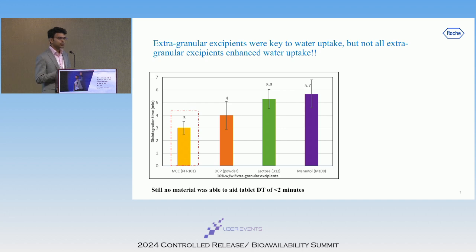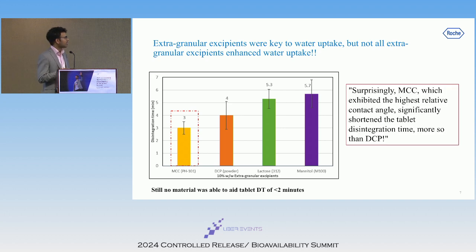Surprisingly, when we do the disintegration studies, we see that MCC, although it had the highest contact angle, demonstrated the best tablet disintegration performance. So this clearly suggests that there are more attributes than just hydrophilicity of a material at play, and we clearly don't understand what leads to an optimum water uptake into the tablet.